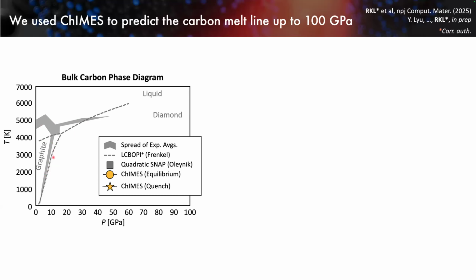Now in the dashed lines, we're looking at what was the state of the art in computational models back in 2008—this is one of the LC-BOP potentials. We see that the melt line has a slope that's a little bit steep with respect to the experiments. The graphite melt line is rather low relative to the experiments, and the graphite-diamond phase boundary is a little bit off.